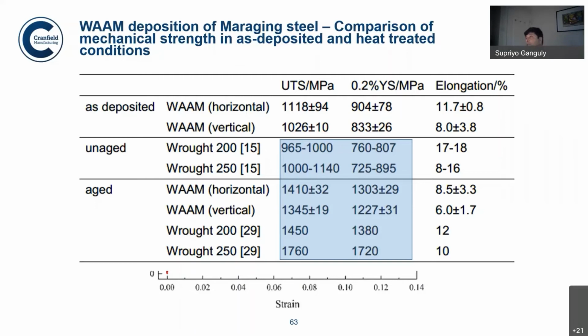So this is basically shown here, and you can see here the different strengths that are mentioned. In as-deposited condition, say the horizontal is 1118, and as-deposited vertical is quite low as compared to the horizontal, which is quite expected. Actually we found them like this. And unaged wrought, which is wrought without any aging, is even less than the as-deposited ones.